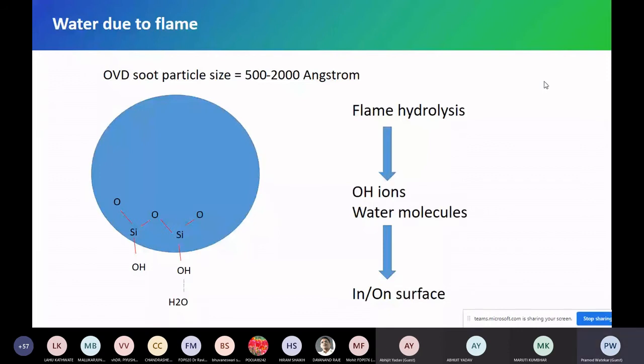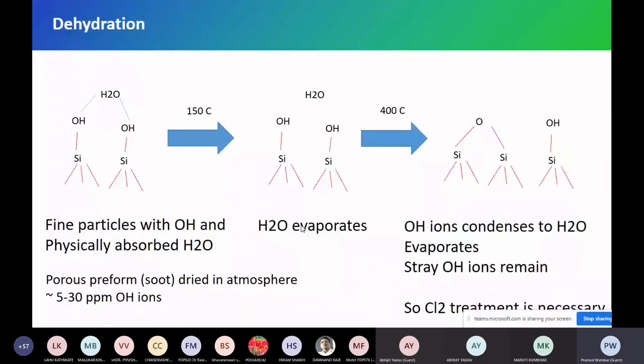If there is OH or water molecule, then it will increase attenuation at 1383, and so it will increase attenuation at 1310 nanometer, which is used for FTTH communication. It also increases attenuation at 1550 if its tail goes there. That is useful for long length, terrestrial communication. So it's very important to control these OH ions in optical glasses. Otherwise, they will appear there. Okay, so what we do is dehydration. We take the glasses, heat to 150, then gradually increase the temperature. That is called dehydration.